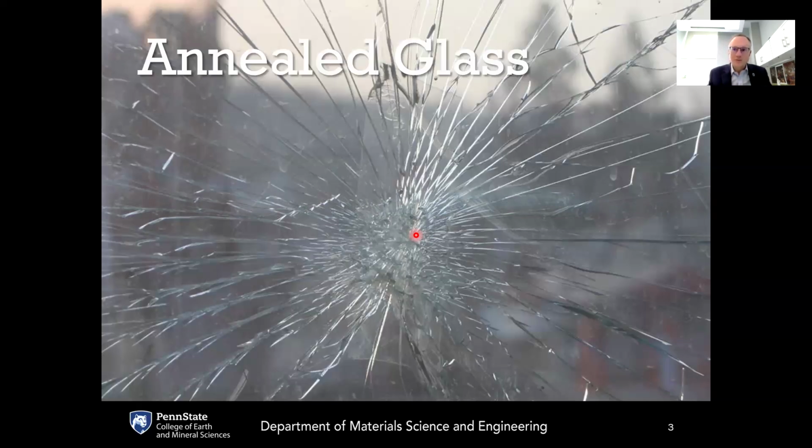So when glass goes beyond that elastic limit, it needs to release that energy in some other way. And the way the glass does that is by breaking. It's by creating these new fracture surfaces, by breaking apart the bonds that are holding the glass together and forming these new fracture surfaces where each of these cracks exist. And that's the way of transforming the kinetic energy of this incoming baseball or rock, transforming that into surface energy by forming cracks.